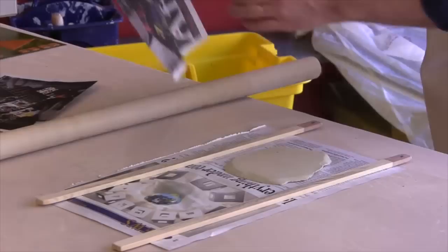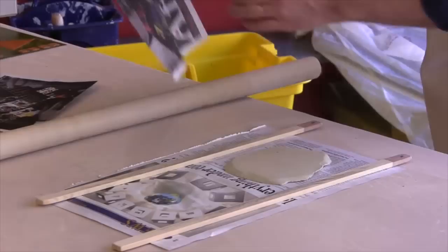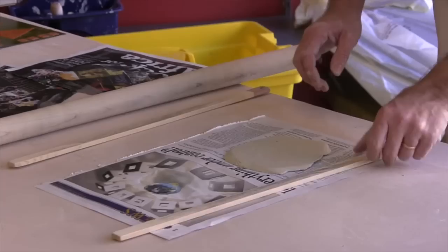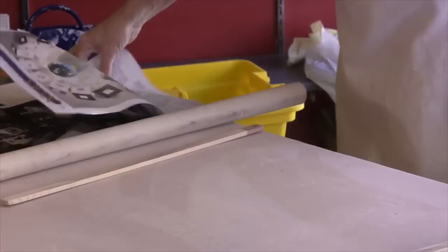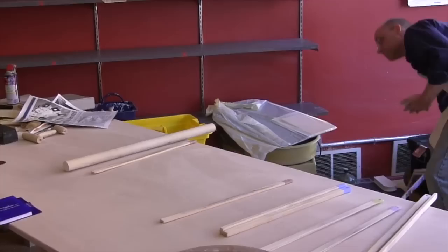The paper is great because it takes a little bit of the moisture out each time. I take a fresh sheet of paper each time because I don't want to get wrinkles in there. When you're working as thin as this is, those wrinkles can turn into perforation areas where it's really easy for the clay to break. So that's what we've got.